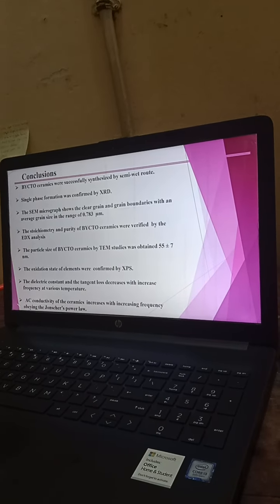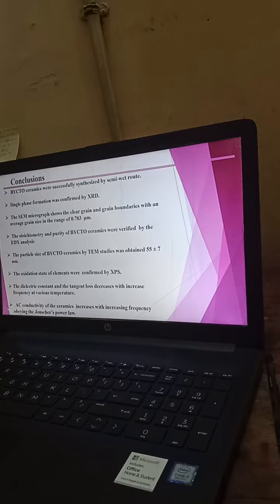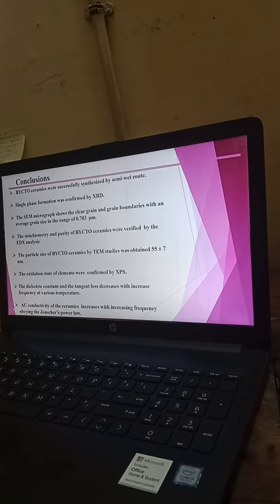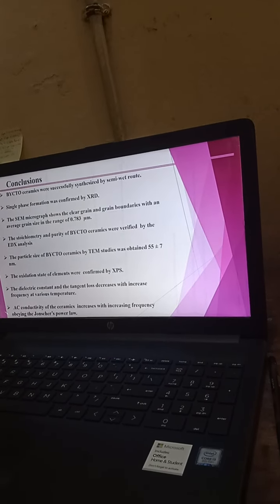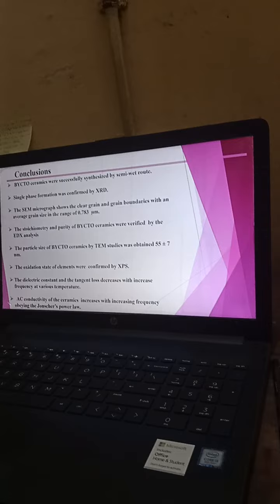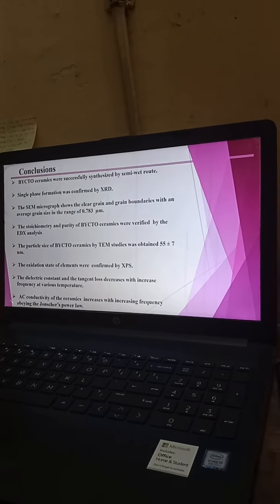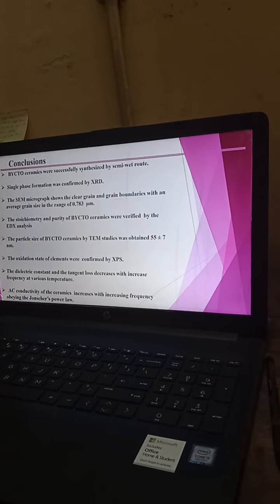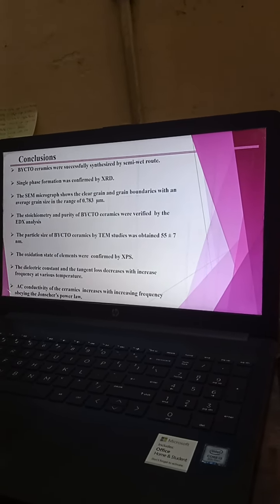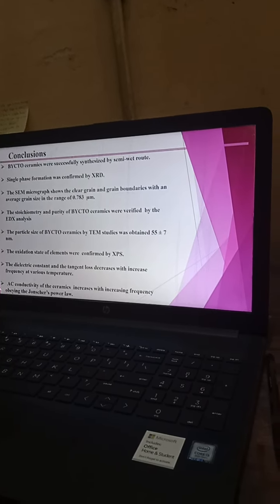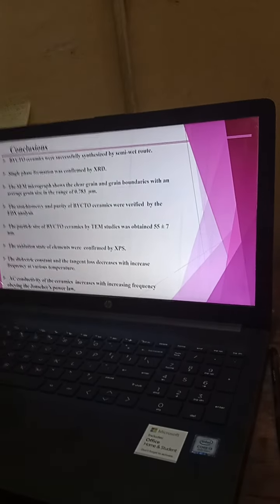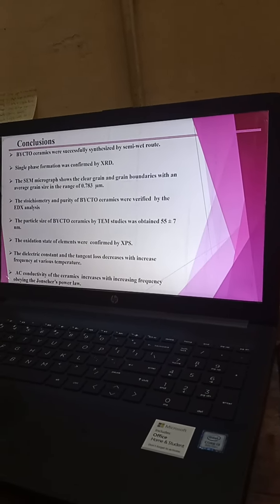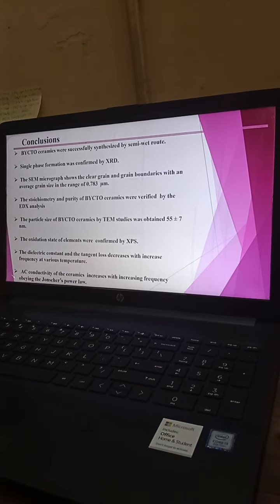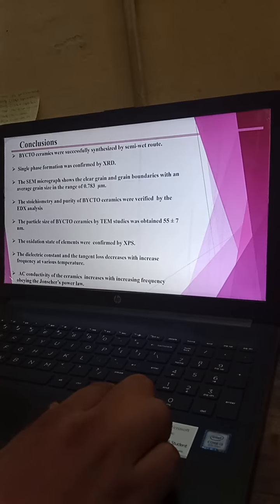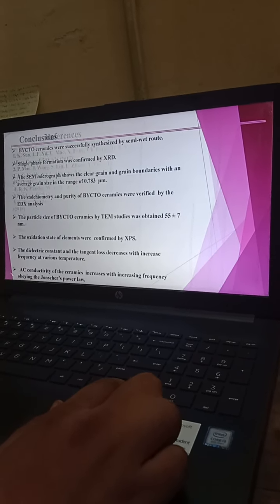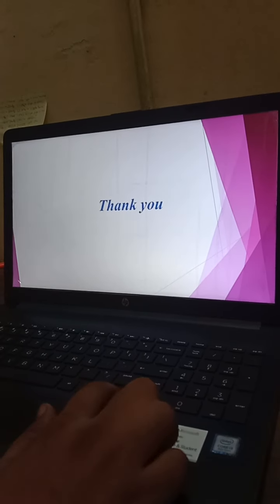So, conclusion: BYCTO ceramic was successfully synthesized by the semi-wet route. Single phase formation was confirmed by XRD. SEM micrograph shows clear grain and grain boundary with average grain size in the range of 0.783 micrometer. Stoichiometry and purity of BYCTO ceramic were verified by the EDX analysis. The particle size of BYCTO ceramic by TEM studies was 55 plus minus 7 nanometer. The oxidation state of the elements was confirmed by XPS. Dielectric constant and tangent loss decrease with increasing frequency at various temperatures. Last one, AC conductivity of the ceramic increases with increasing frequency obeying the Jonscher power law. These are the references. Thank you to all of you.